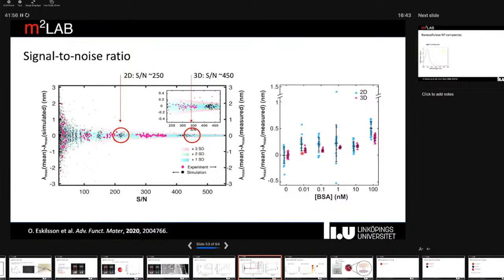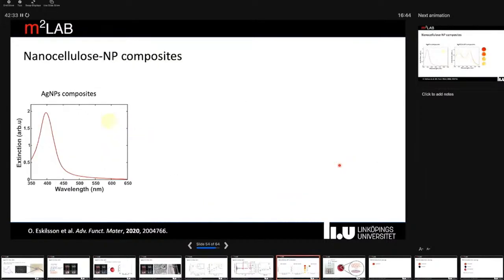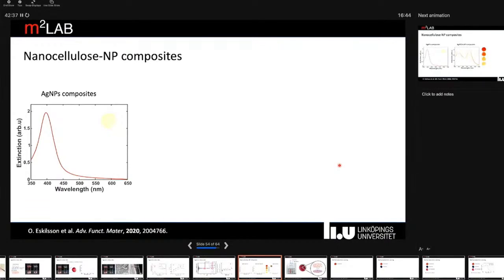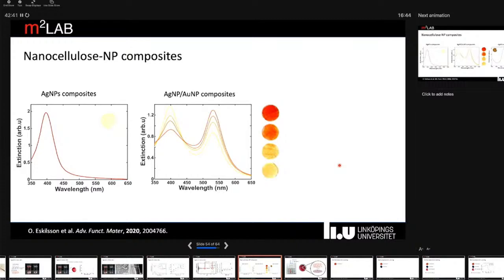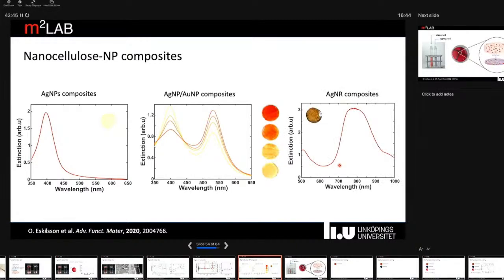And what this in practice means is that we have a much better reproducibility when we measure things, because there is less influence from noise. If we just look at an example here where we adsorb bovine serum albumin on the surfaces, we see that there is quite small variation in the pink three-dimensional data, whereas in the blue two-dimensional data there are quite much larger variations due to the lower signal to noise. But with this technique, with the self-assembly of the particles in the membranes, we can also essentially immobilize all sorts of different kinds of particles, or a combination of particles, to make more elaborate nanoplasmonic materials. So that we thought was quite interesting.